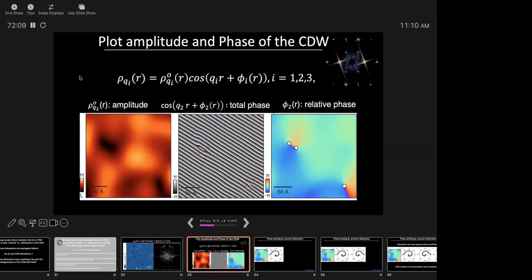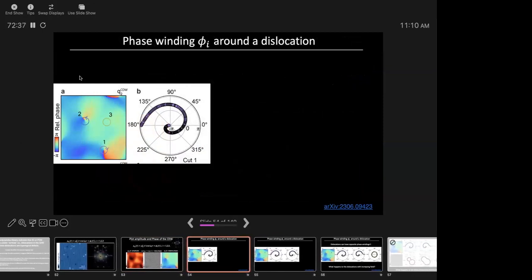If the charge density wave were homogeneous everywhere in space with no phase shifts, then this relative phase would be 0. All you would have is a cosine term, that's it. So this relative phase actually captures any phase shifts in the charge density wave, and a phase shift is a dislocation, okay? So you can see already for this topography, you have a pair of dislocations here. Now, let's talk about the phase of these dislocations. Because we can measure the phase, we can plot it as a function of angle as we wind around one of these dislocations. So here we're winding around this dislocation, and you can see that the phase winds by 2 pi as we go around.